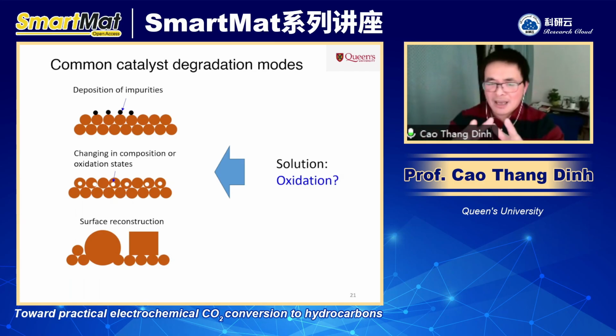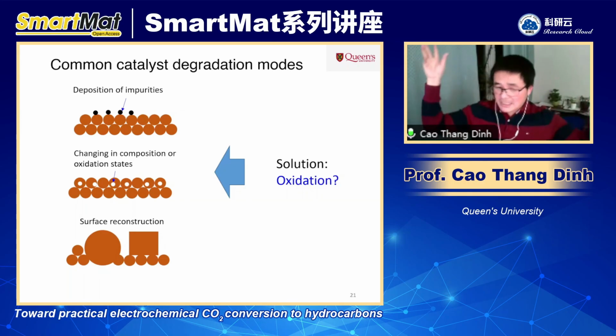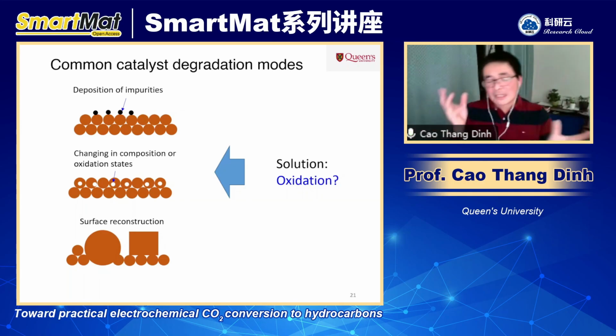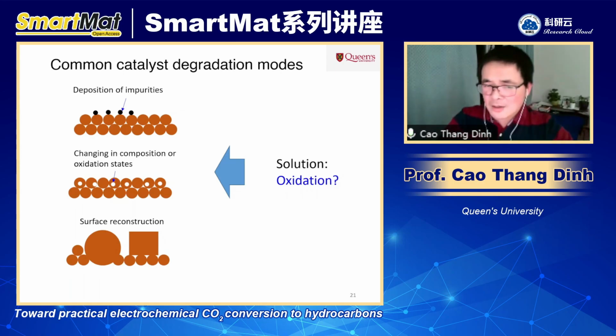If you have the oxide catalyst, now you run the reaction, it reduces to a metallic surface. Now, if you oxidize it, you can resume the oxide phase, right? And also with the surface reconstruction, you can turn it into the oxide and then you reduce it. This can also change the surface and it can change the activity as well, which we will discuss later on. So, three different challenges, but potentially we just need one solution for that.